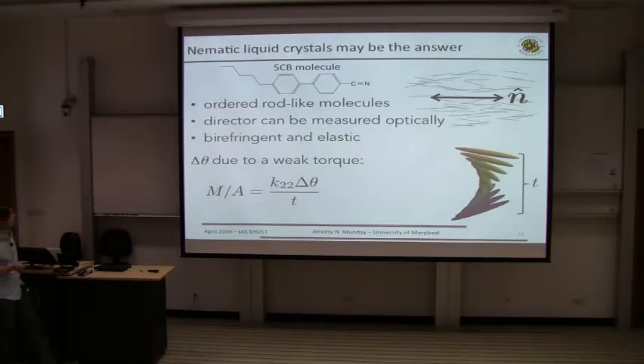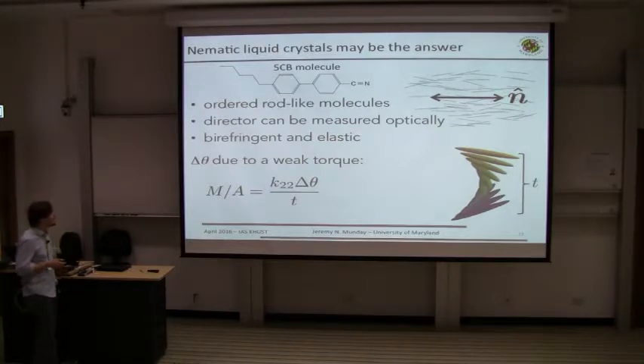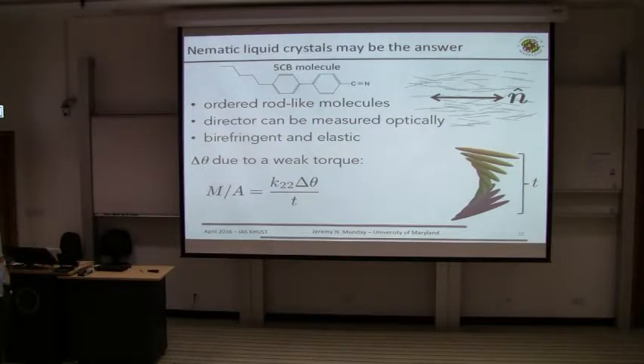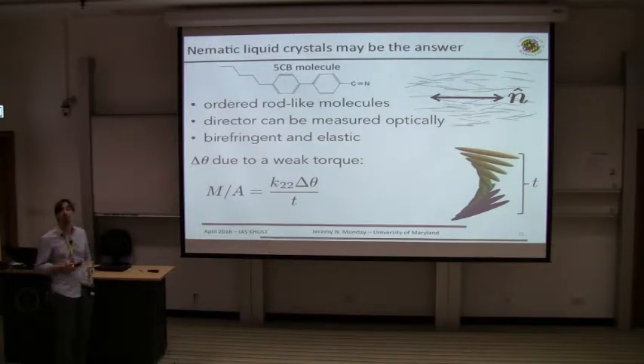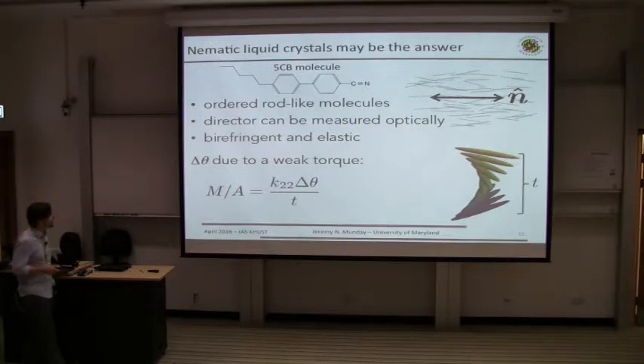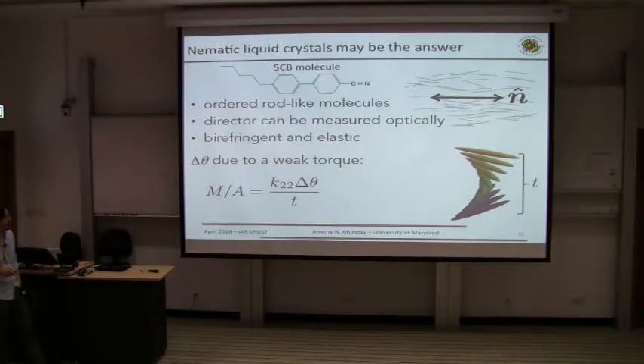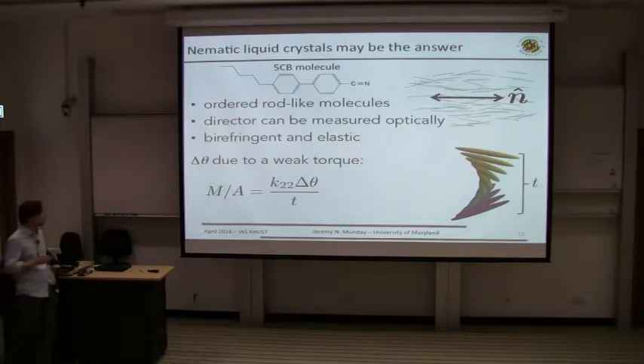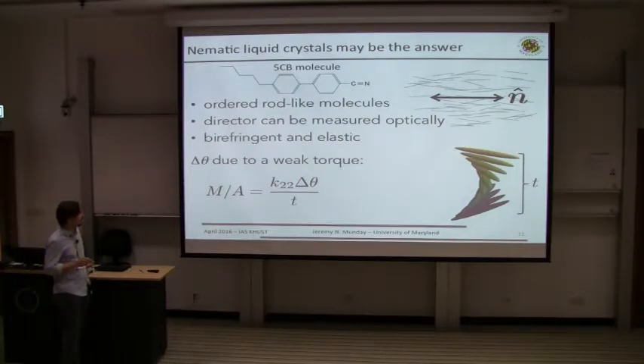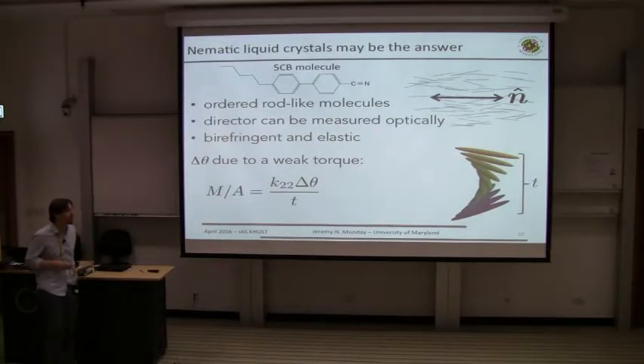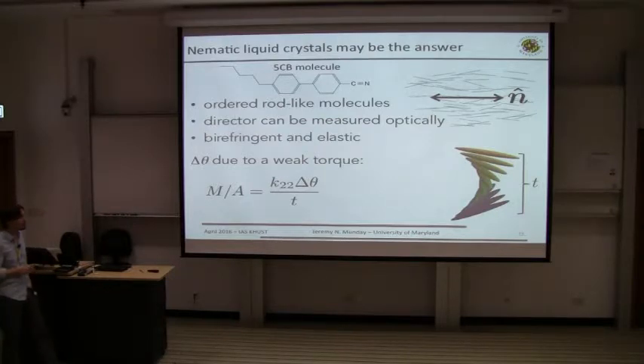So the way that we're thinking about this, one solution might be using nematic liquid crystals. These are materials, molecules basically, that have a long direction and a short direction that have a different index of refraction associated with them. The thing that's nice about this is it can serve as a birefringent material, and it can also serve as a sensor, like the torsional rod that you would normally be thinking about. When you put these together in a bulk, they can be described by an elastic twist constant that gives you a torque per unit area that goes as this elastic twist constant times the angle over some thickness of this bulk crystal.